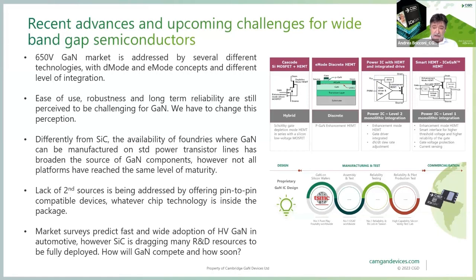And that is because there is not a specific reason why GaN cannot be as reliable or even more reliable than silicon carbide or silicon. It's simply a matter of time and a matter of progress in the technology innovation. But in terms of voltage, it is heavily derated. So a 600 volt device typically has a breakdown voltage well above 1 kilovolt. And so far, the industry has demonstrated that GaN transistors can be very reliable. It's a matter of time.